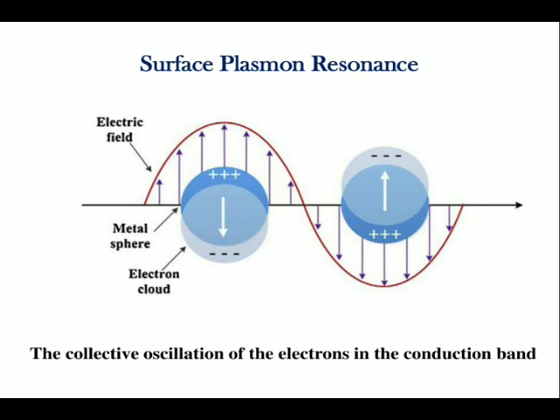Usually in the case of gold nanoparticle, the surface plasmon resonance is in the range of 520 nanometer. When the size of the gold nanoparticle changes from 10 nanometer to 50 nanometer, the maximum extinction of the SPR band shifts from 517 to 532 nanometer in the visible region, which indicates that the intensity and absorption band of gold nanoparticle are concentration and particle size dependent.